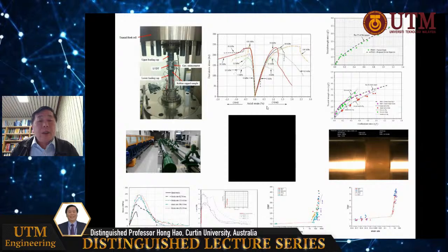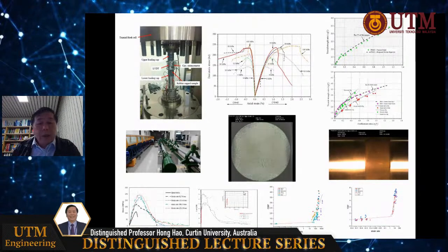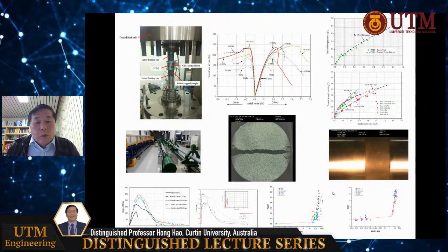So we did the dynamic triaxial test to try to get its complex mechanical properties, such as equation of states, damage surface, and strength theory. We also did the dynamic test, the split Hopkinson pressure bar test. Just to show you, this is the split test, so the splitting damage, and this is the compression test by split Hopkinson pressure bar, to get the dynamic material properties or dynamic strength increase factor.